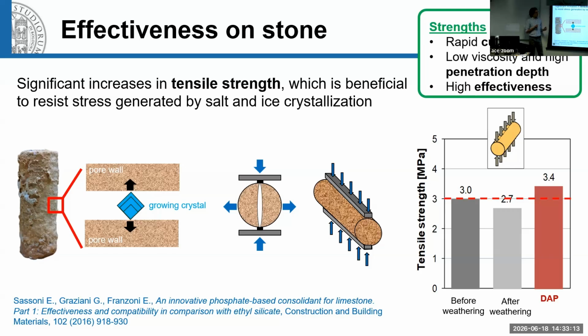Because problems due to salt crystallization, ice crystallization, and so on arise because of the low tensile strength of the stone. When we have a crystal of salt, for instance, or ice growing in the pore of the material, the crystal is growing, pushing against the pore walls. So from the material point of view, it's as if I'm doing a kind of tensile test in this direction, okay? So I can improve the resistance of the material to salt crystallization and so on if I'm able to increase its tensile strength.